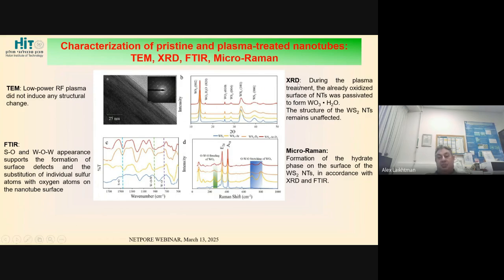For XRD, again, the structure is preserved. The structure of the nanotubes is preserved. But then we observed a peak which is related to WO3·H2O. So we have some kind of passivation of this oxide with water molecules which were residuals from the atmosphere, because we did not perform any annealing.